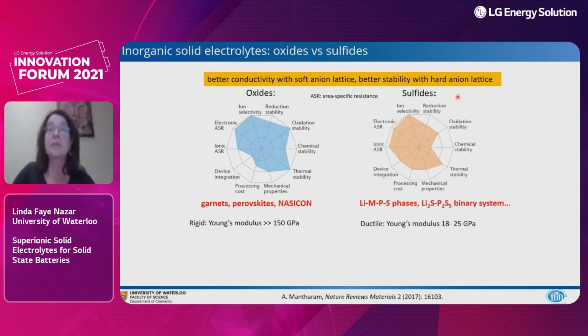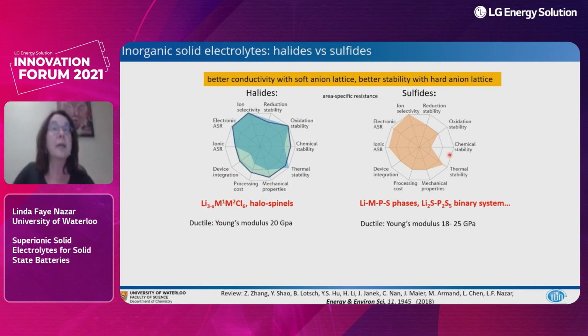On the other hand, sulfides are relatively ductile, and these include a range of lithium metal thiophosphate phases and thiophosphate glasses, and these have Young's modulus significantly lower, in the region of 18 to 25, but they have poor oxidation stability and thermal stability. But it's that ease of processing that has basically made them the electrolytes of choice. And in the last few years, halides have emerged, which are sort of a compromise. They have good oxidation stability, good thermal stability, and a moderate Young's modulus, which is in the range of the sulfides, such as argyrodite that I'll be talking about today. And I'll be highlighting these at the end of the talk.